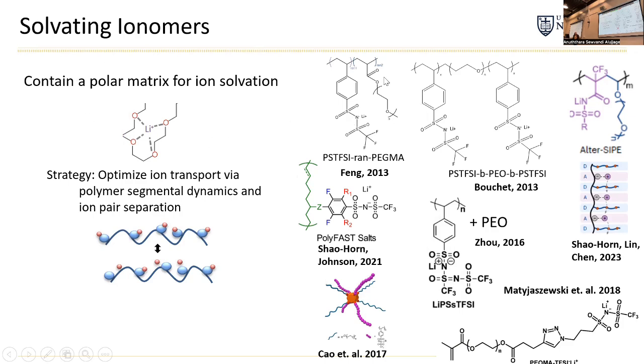And how these polymers work is that part of the polymer is polar, okay? And the polar matrix is very important for ion solvation. So lithium here in the schematic, you can see it surrounded by, this is actually polyethylene oxide. You're familiar with that chemistry. But these oxygen atoms here have pairs of electrons on them that interact with the lithium cation. So lithium in polyethylene oxide likes to make a shell of like 4 to 6 oxygen atoms.